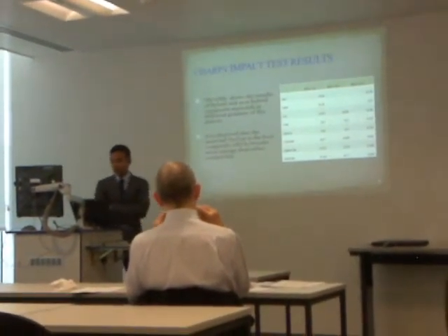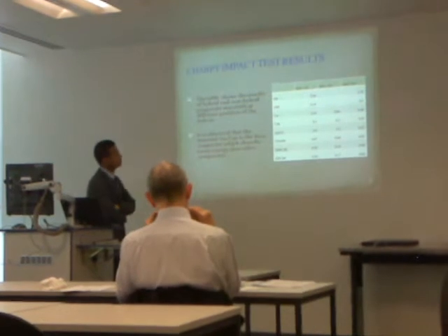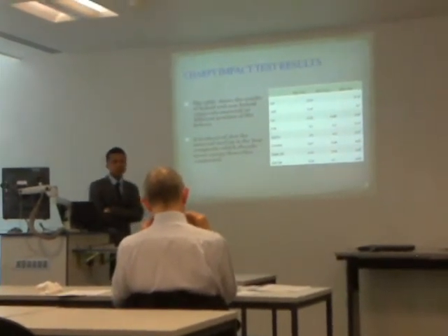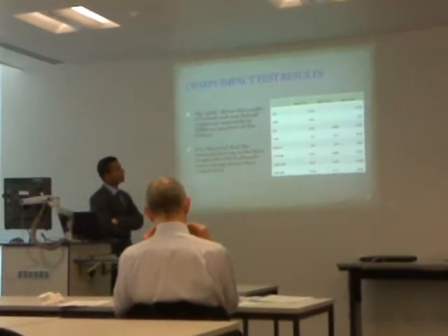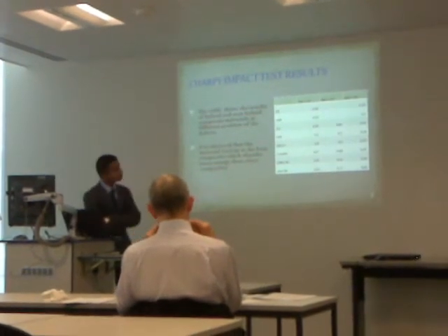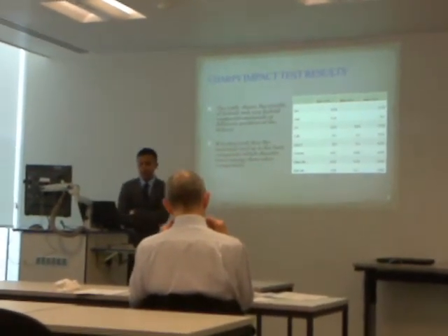The Charpy impact test results. The table shows the results at three different defects, between layers 3 and 4, between layers 4 and 5, and between layers 5 and 6. For the material G0, G90, we have taken only 4 layers, and the defect is placed between layers 2 and 3, and 3 and 4. From the table, we can say that the best composite material is G0, G90, which absorbs the most energy.